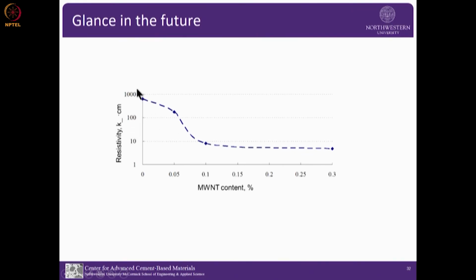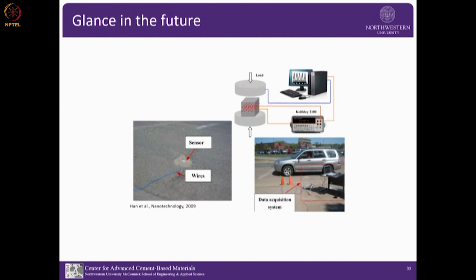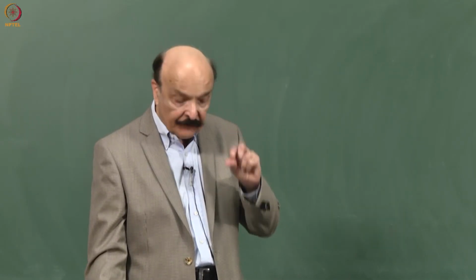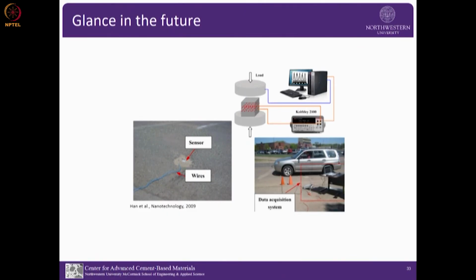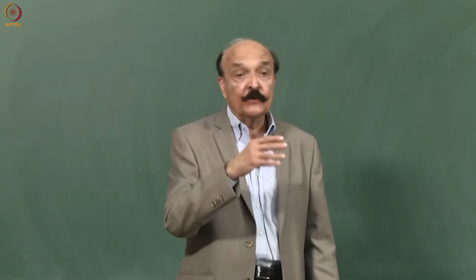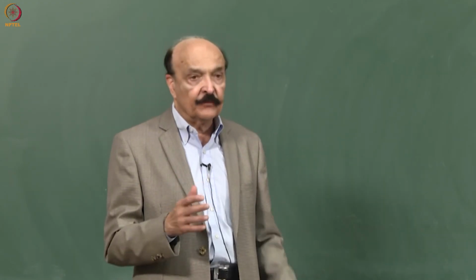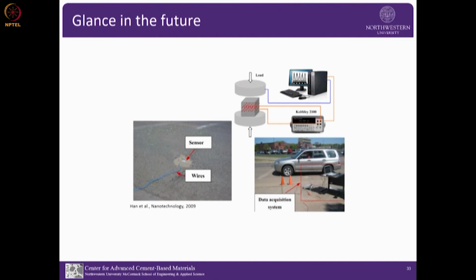This work was done at Southeast University in Nanjing, with multi-wall carbon nanotube. What is the resistivity without any nanotube? You can see at 0.1% the conductivity has increased by 2 orders of magnitude, or resistance has gone down. So that's very effective for using this material as a sensor, and many people have done work. This is not our work, but somebody in a highway department in Minnesota. This is cement with 0.1% carbon nanotube, and you apply compressive load repeatedly and remotely measure and calibrate the change in resistance. So when you embed this as a sensor, when a car goes through, there is a change in resistance, and then a second car, and you can measure, for example, the speed of the car remotely. There are many other ways that people can use this as a sensor. So that's another property of carbon nanotube.